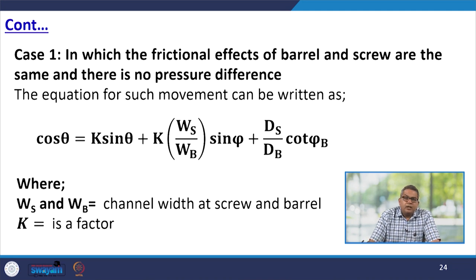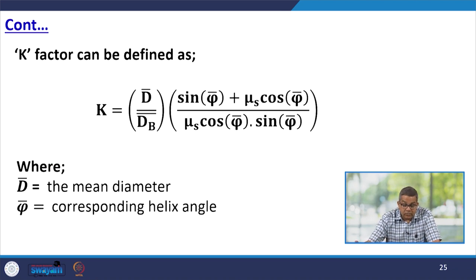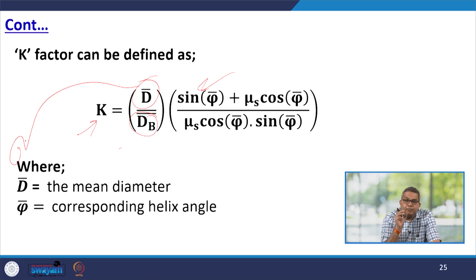Now let us discuss a couple of cases. In case one, the frictional effects of the barrel and screw are the same and there is no pressure difference. The equation for such movement can be represented mathematically as cos theta is equal to k sin theta plus k ws over wb into sin psi plus ds over db cot psi b, where ws and wb are the channel widths of the screw and barrel, and k is a factor. Now the question arises of how we can determine the k factor. This k factor can be determined as k is equal to d over db sin psi plus mu s cos psi over mu s cos psi into sin psi, where d is the mean diameter and psi is the corresponding helix angle. We have already discussed the helix angle in the previous slides.